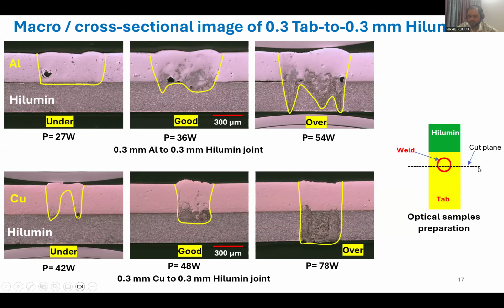I have done this cutting using a high precision cutter, and the sample is mounted in the same manner as it is showing, then cloth polished and paper polished, and they have captured the weld bit under the optical microscope. This kind of image is captured after using the optical microscope. So this is an example of underweld, because you are not getting sufficient penetration. This is just touching the laser beam to the bottom sheet. So this hardly penetrated the bottom sheet, but this is an example of good weld. And this is an example of the overweld.